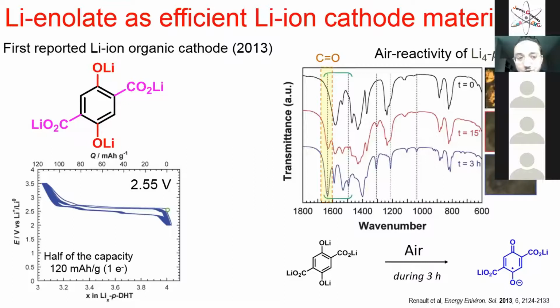But what happens to the molecule when you expose it to air? It gets oxidized, actually. Here I'm showing you the air reactivity that we monitored with IR spectroscopy, and you can see after 3 hours of exposure in air, you have the formation of a carbonyl bond, and this characterizes the oxidation of this molecule. So here we just need to have the same molecule, but it should be stable. How can we do that?